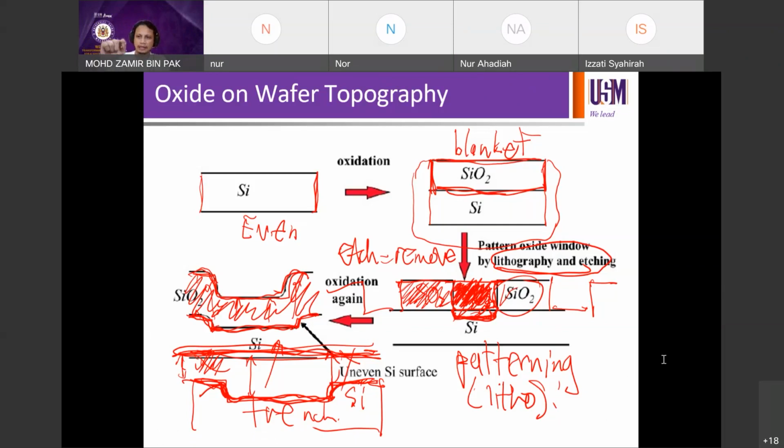It will be a bit rounded. If the silicon underneath is sharp, like a square-shaped trench, the growth will not be sharp going in. It will be a bit rounded, because there is a smoothening effect at the trench. It follows the trench but not exactly, because it's not the exact process. It will have some diagonal component of the growth rate, if you like. So it will be rounded but it will still go into a trench. It will follow the underlying topology.